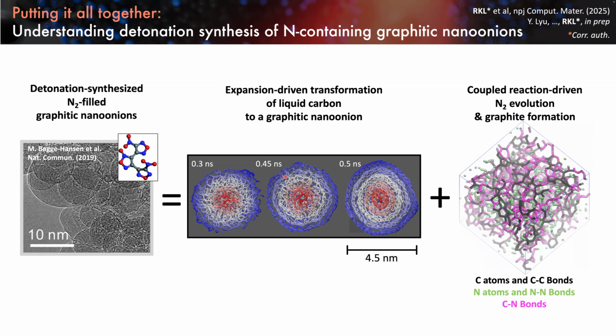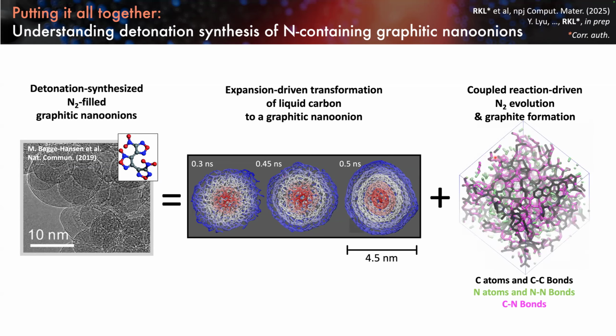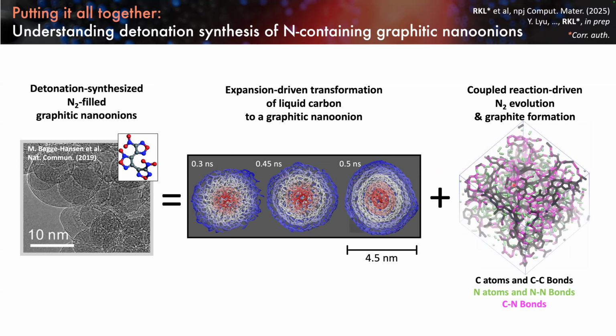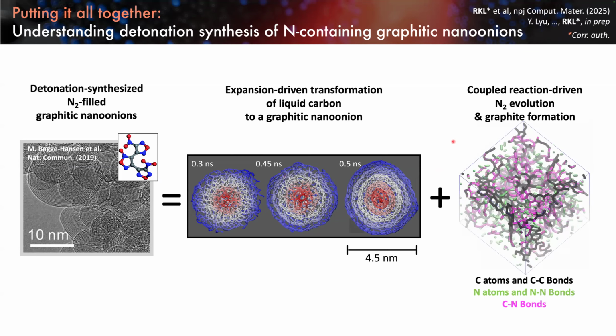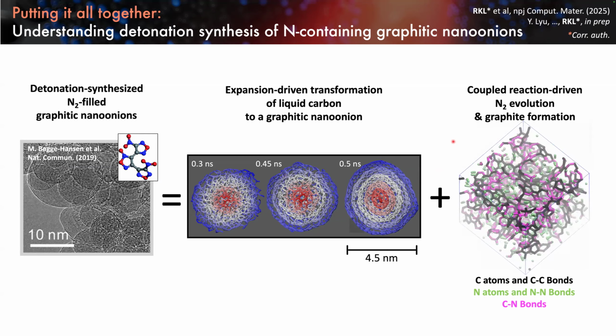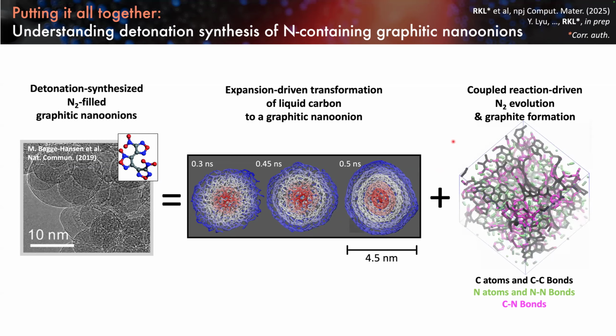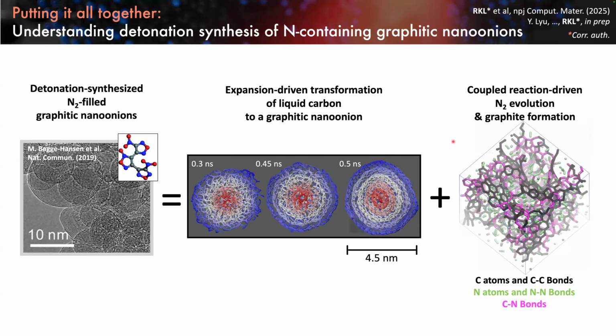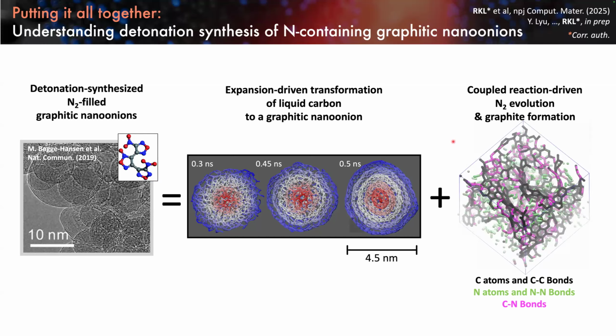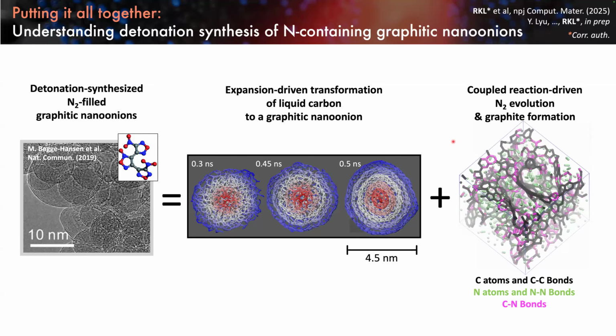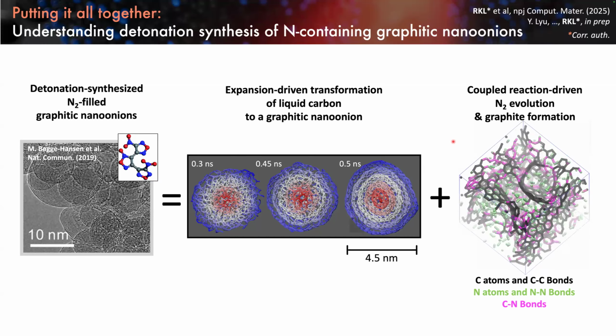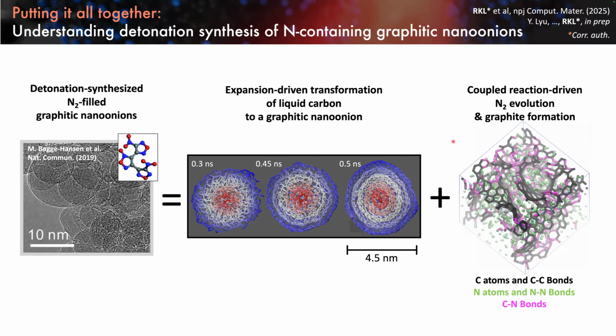So this is an example of one of those simulations. Where you see pink, that's a carbon-nitrogen bond. Black is carbon-carbon, and those little green things rattling around are nitrogen molecules. In fact, what we found is that for most of our simulations at high temperature, the carbon and nitrogen remained very well mixed with one another.